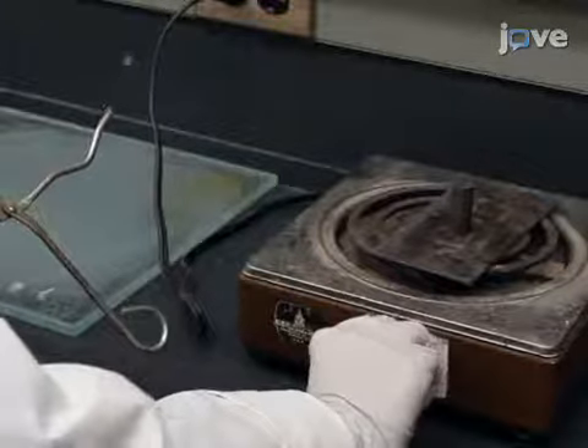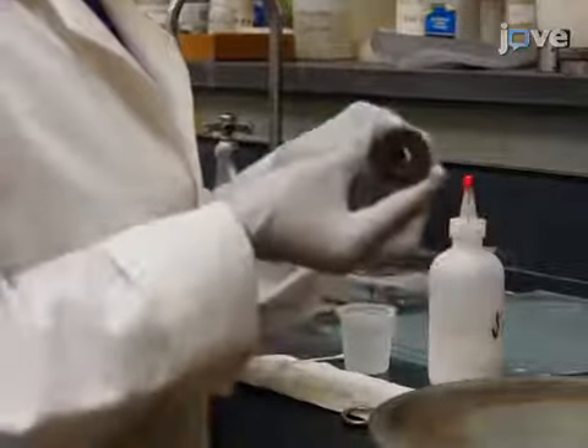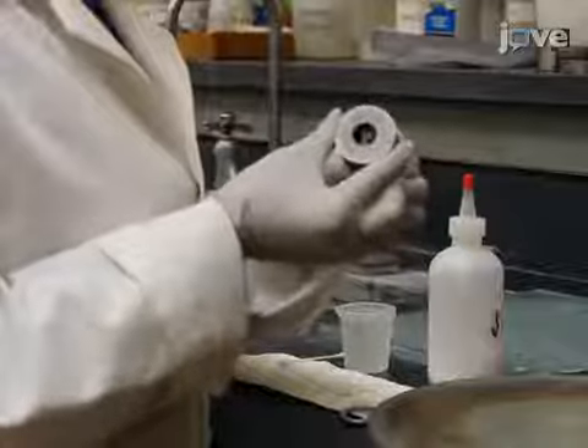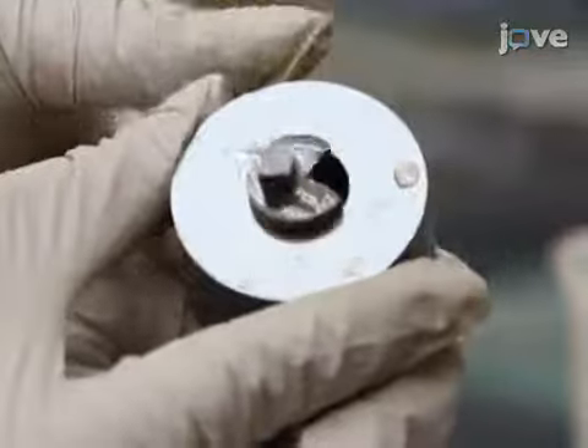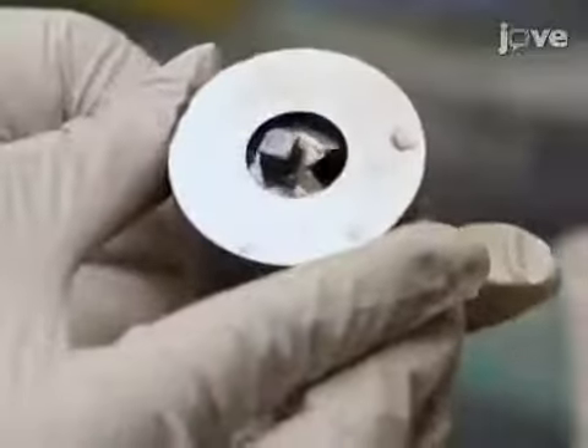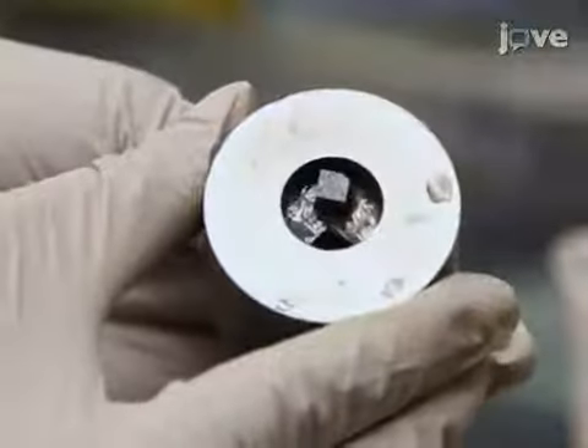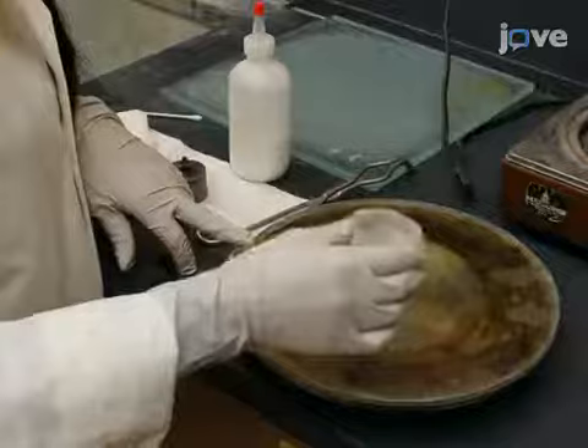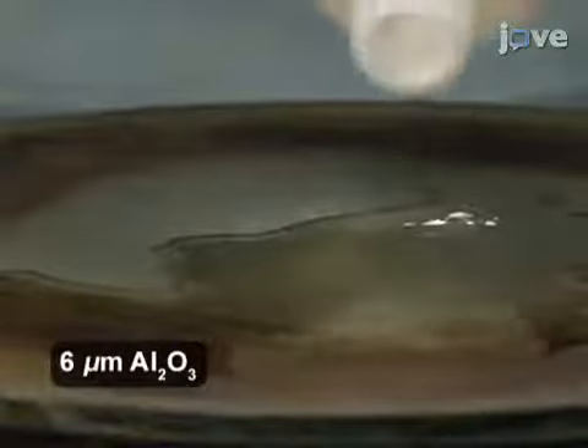After cooling to room temperature, tightly fit the rod into a metal cylinder with a larger outer diameter, so that the bottom surface of the cylinder and sample can be polished together to guarantee the flatness of the sample surface. Wet a plexiglass plate with tap water, and sprinkle 6 micron aluminum oxide powder onto the wet surface.